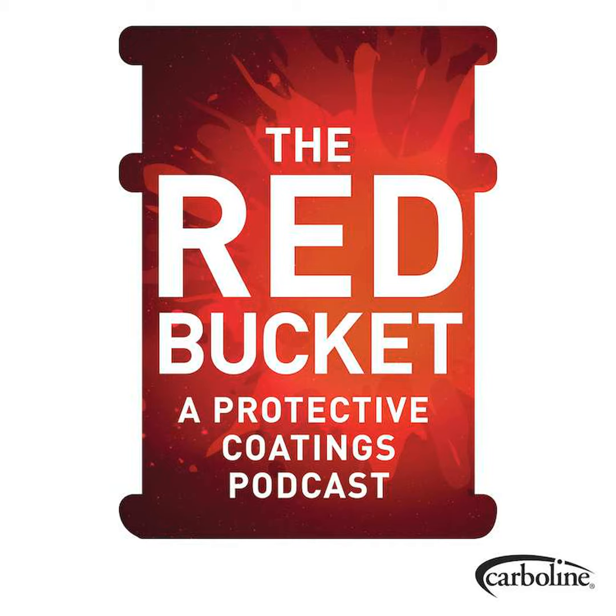And that stripe coat that you speak of, this is also commonly used on welds, irregular areas, geometries, this sort of thing, because you're physically wetting out that material on that weld or at that area, because again, a lot of products don't have the flow and wetting characteristics to do that all on their own. So you physically do it with the brush prior to putting your primary lining over the top, and that ensures that you had good wetting out and adequate coverage of that weld seam, basically.